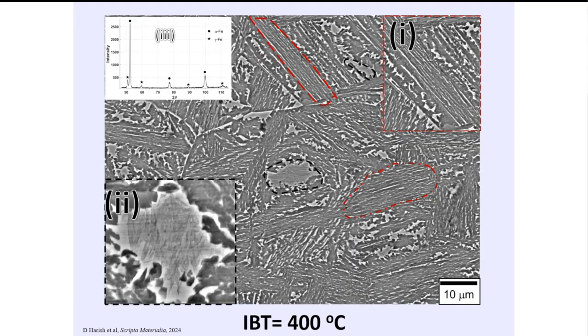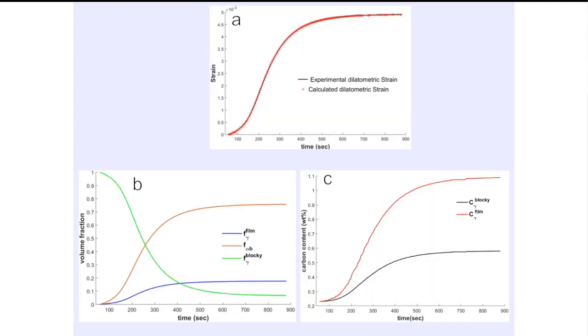We believe therefore that the bainite that forms in at least these alloys at such temperatures has a tetragonal structure. The carbon concentration obtained from this analysis is about 0.18, which matches very well with the X-ray results. We also know that when bainite forms, it has a certain amount of retained austenite in film form as well as in bulk form. The carbon concentration of these two morphological variants differs, and qualitatively it is known that film austenite has higher carbon than blocky austenite.